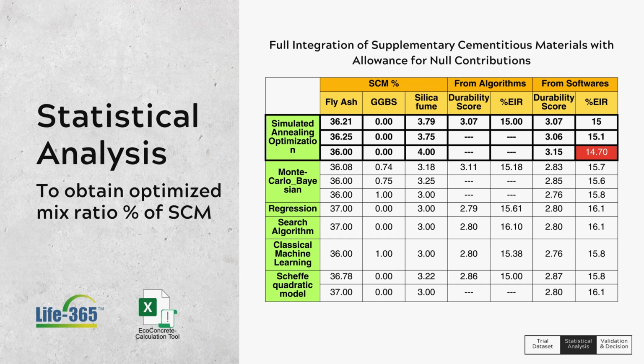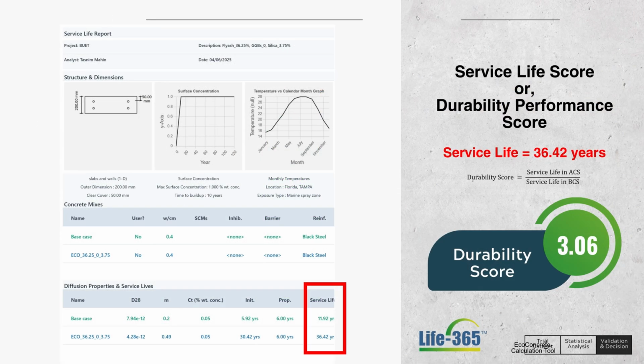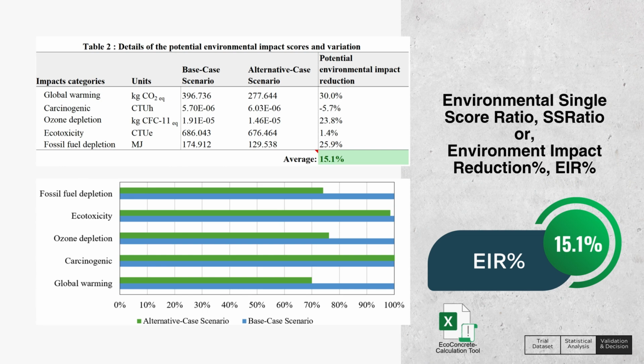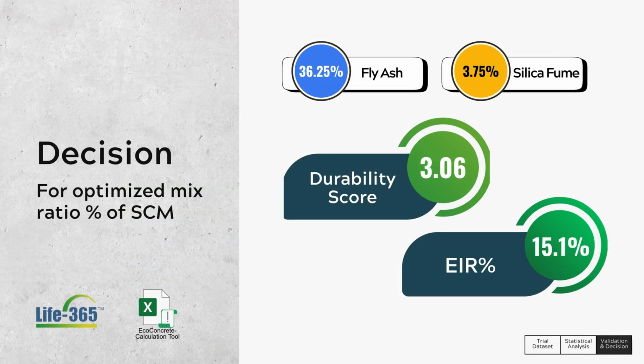We can see that we achieved a superior durability score of 3.15, but it failed the EI criterion with only a 14.7% reduction, making it non-compliant with the sustainability threshold. Instead, we chose the closest mix ratio with a 3.06 durability score and 15.1% EIR. And this is the software validation and service life report. And this is the EIR report. And this is our final optimized mix ratio.